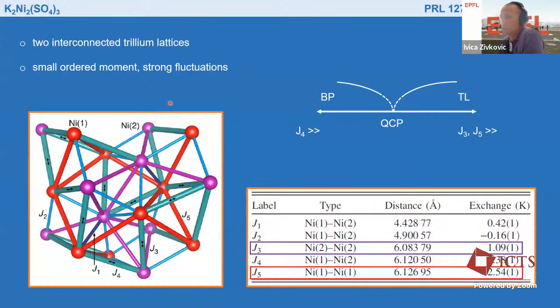2 scenarios, right? So we have small ordered moment, and strong fluctuations in the system. So we should be somewhere close to a critical quantum phase transition, where on the one hand you have a dominant J4, which is the interaction between the trillium lattices. And if you look at it, J4 is basically forming a bipartite lattice. So that means that this is an antiferromagnet in this regime.